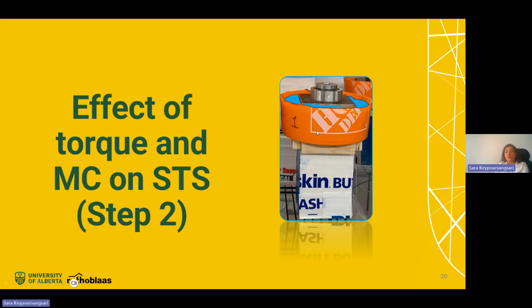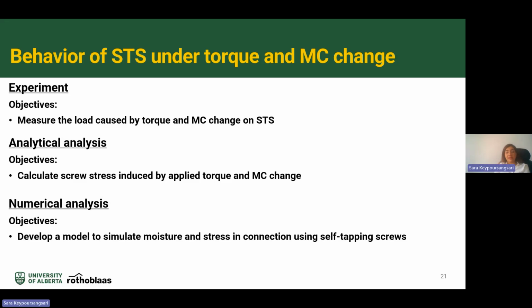In order to increase the level of the moisture, we increased the height of the bucket, and you can see it in the next slides. The objective of this part was measuring the load caused by torque and moisture content change on self-tapping screws. Same as the previous steps, we used the analytical model and calculated the stress on self-tapping screws. And finally, in this stage, we developed a numerical model to simulate the moisture and also the stress on self-tapping screws.